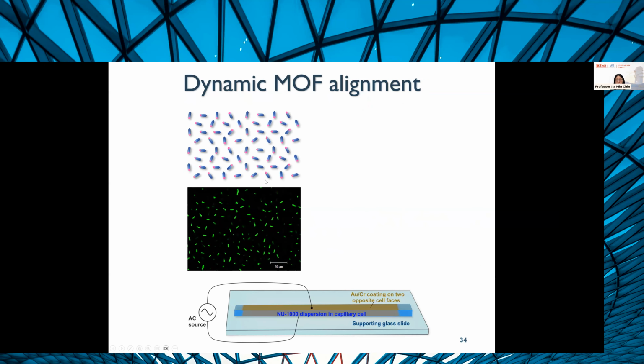But what we did was we first took NU1000, and this MOF is a really nice workhorse because it's very easily synthesized in a monodispersed fashion. Also, it happens to be fluorescent, so one can easily observe it using confocal microscopy. If you disperse these particles in a nonpolar solvent, such as bromobenzene, because these particles still have a zeta potential, you get very little solvent and ion shielding of these particles. So you get electrostatic interactions between these particles, and they repel each other. Because of this repulsion, these particles end up being dispersed in a very uniform manner, and you have basically positional order.